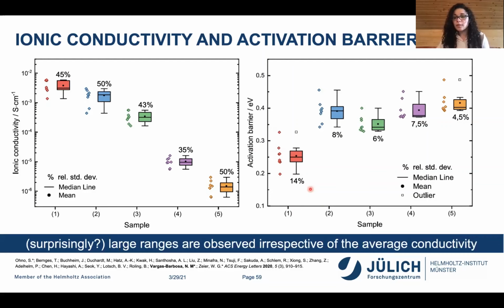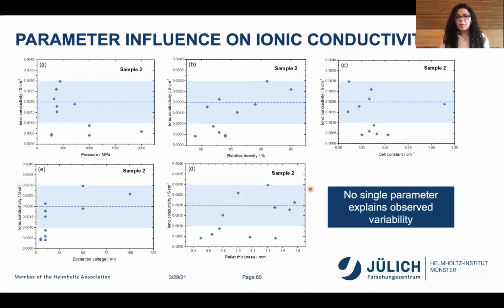But then we tried to look at experimental parameters that could explain this kind of spread. And we really tried to look at everything that we could possibly think of, and we just couldn't find anything. So this is the pressure applied on the powders prior to measurement, a pre-processing kind of pressure. The dashed line here is the average, and this is the spread, the range that the standard deviation is estimated from these data. Here we have the relative density of the pellets. It kind of increases, but it doesn't fully explain it. We looked at things like cell constant, the excitation voltage that people applied during their measurements, and even pellet thickness. We just couldn't explain it.